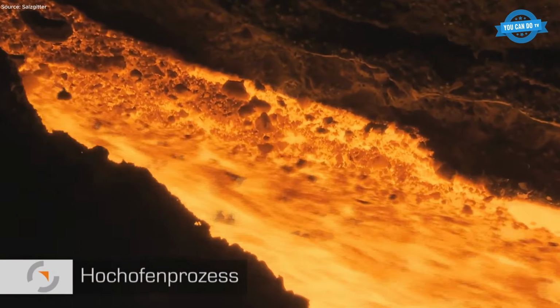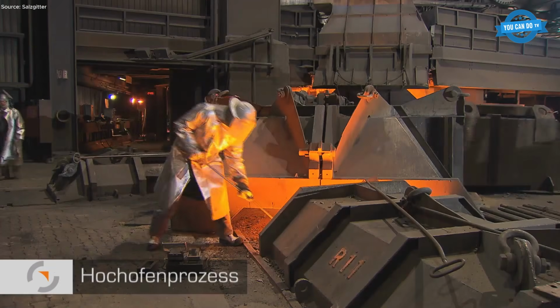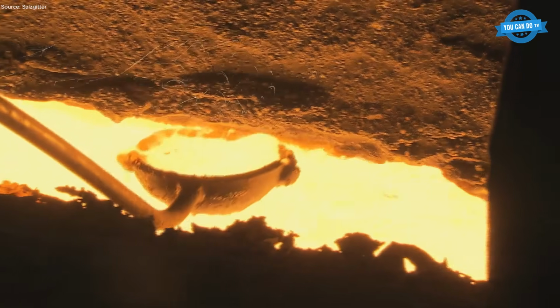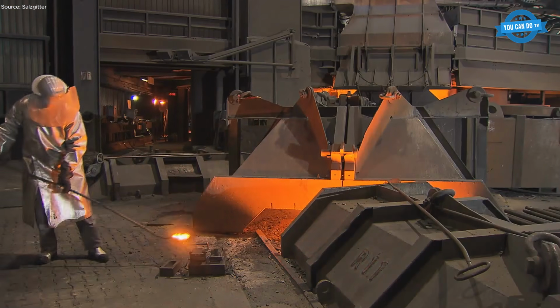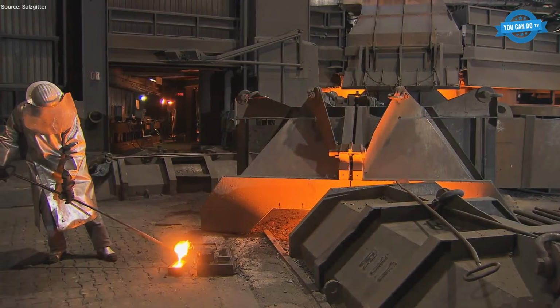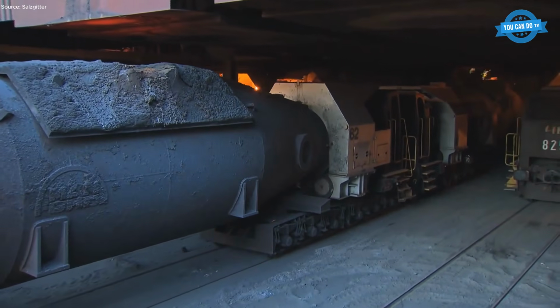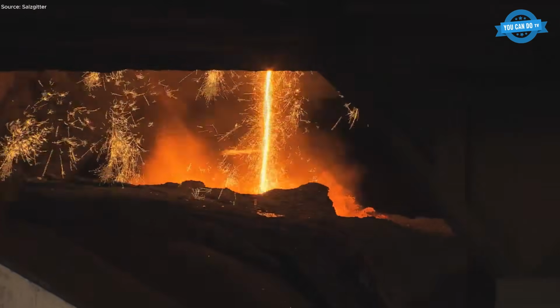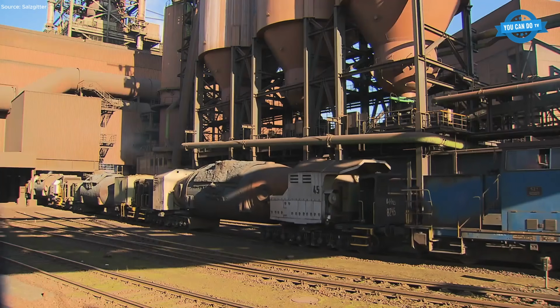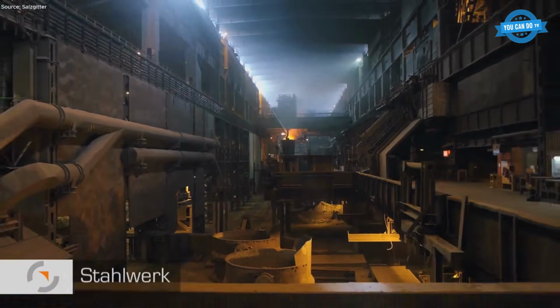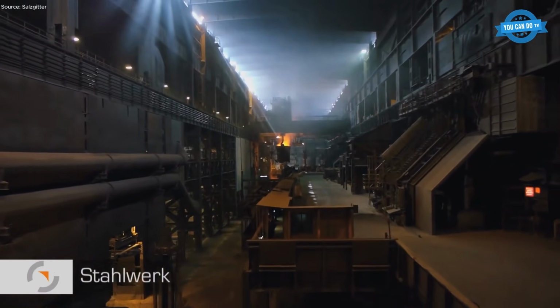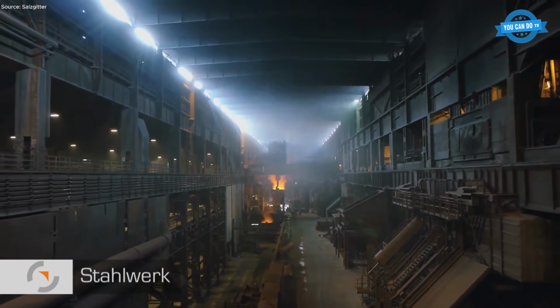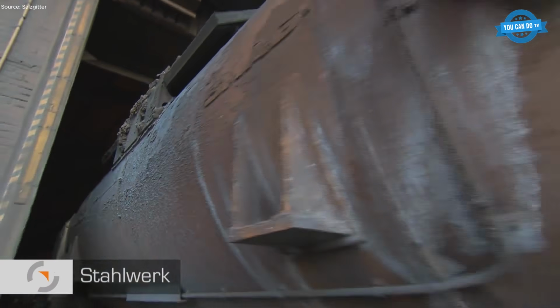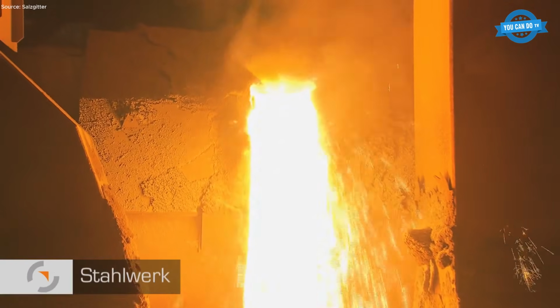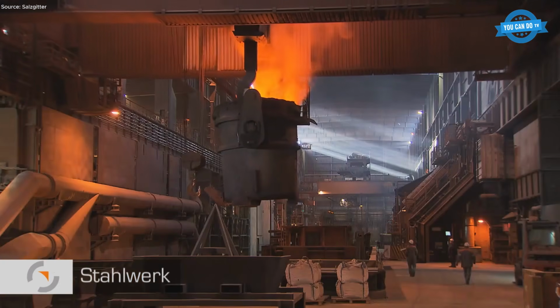Inside the furnace, alternating layers of coke, iron ore, and fluxes are charged from the top through a rotating distribution system. Preheated air at approximately 200 degrees Celsius is injected into the lower section. As oxygen reacts with coke, process gases reaching temperatures near 2000 degrees C are generated. These gases reduce iron oxide, removing oxygen, and enabling metallic iron to form and melt.